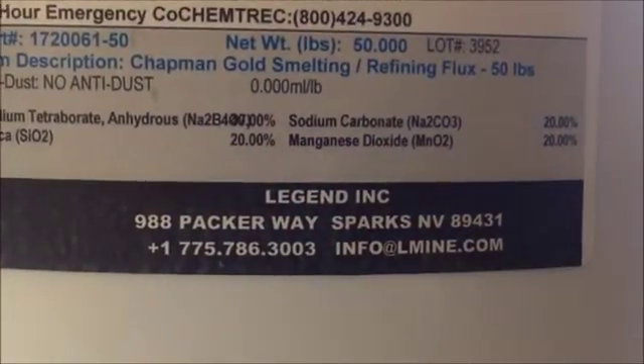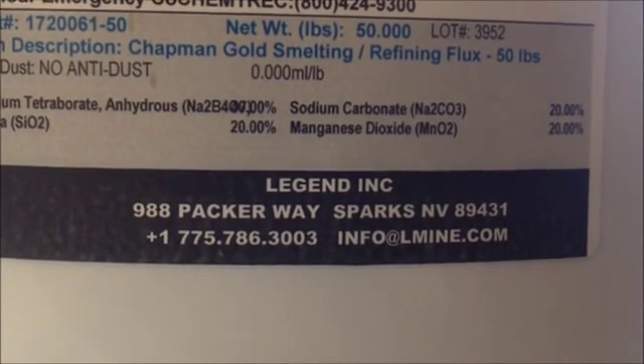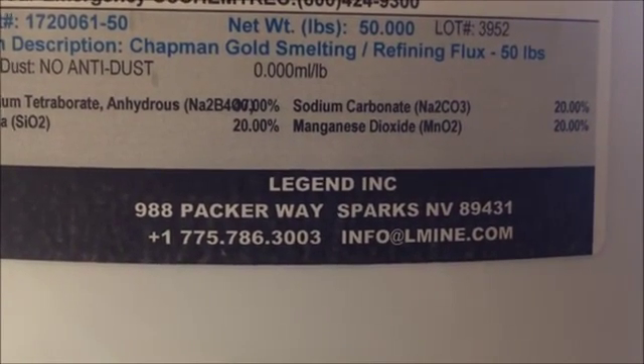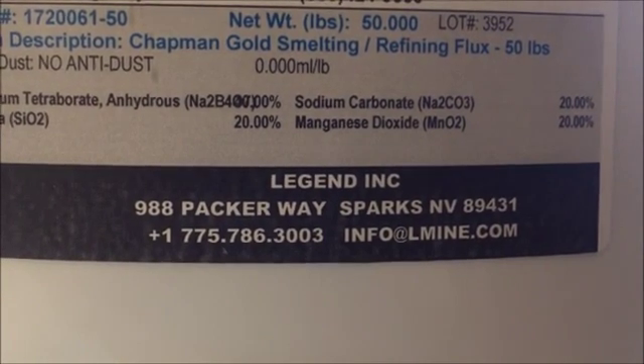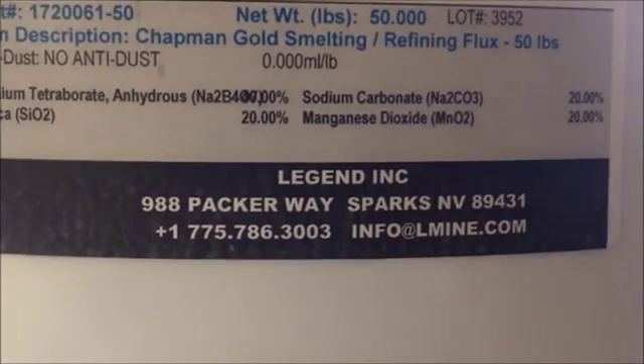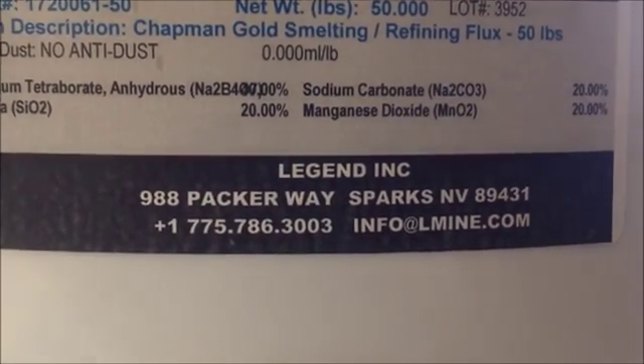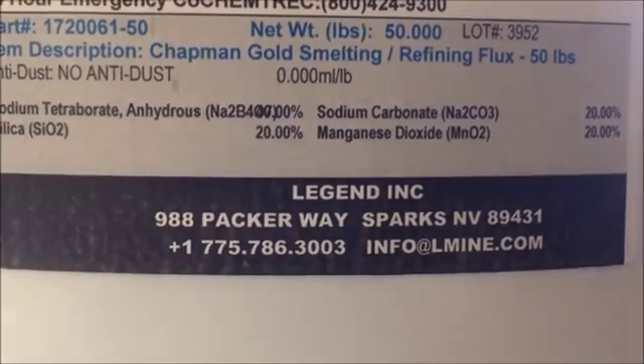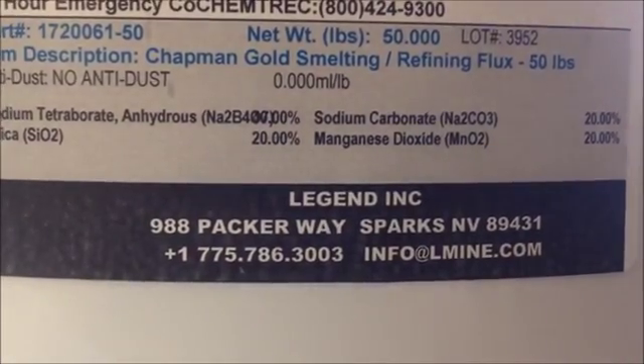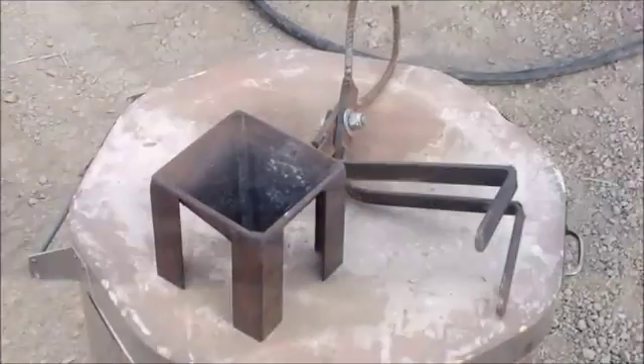So here's the Chapman flux recipe that I'm going to be using. The sodium tetraborate is borax, and it's covered up there a little bit, but it's 40%. Sodium carbonate is soda ash at 20%. Silica is just quartz, and manganese dioxide as an oxidizer.